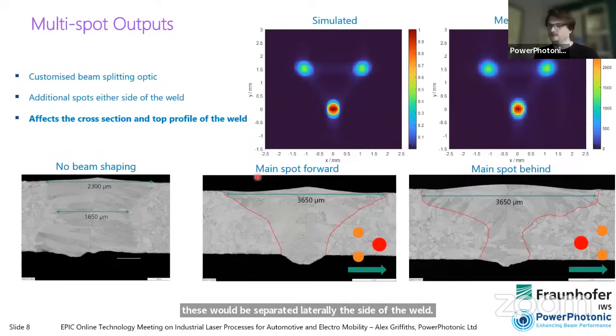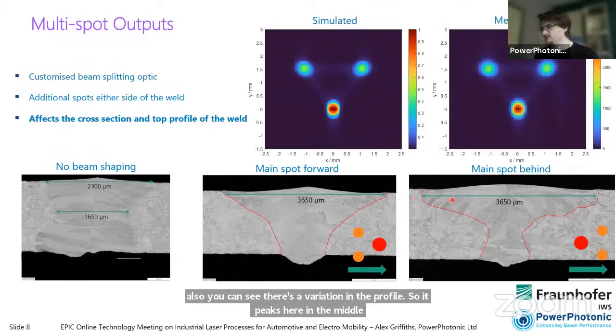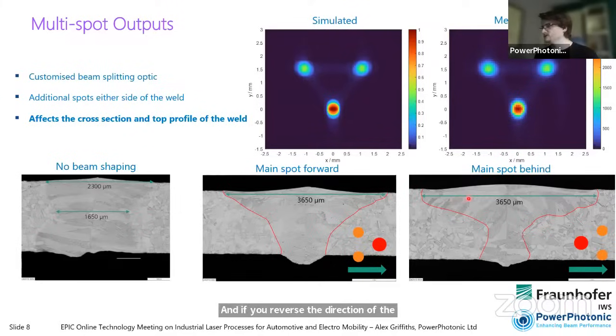This shows a strong influence on the weld's geometry, on the geometry of the weld seam. So here on the left, this is the case with no beam shaping, whereas when we have these additional spots, the width of the seam at the top is much wider. But also you can see there's a variation in the profile, so it peaks here in the middle. And if you reverse the direction of the beam shaper so that the 2 spots lead the main spot, this shape changes as well. So directionality is important, and we can have a strong influence on the cross section.